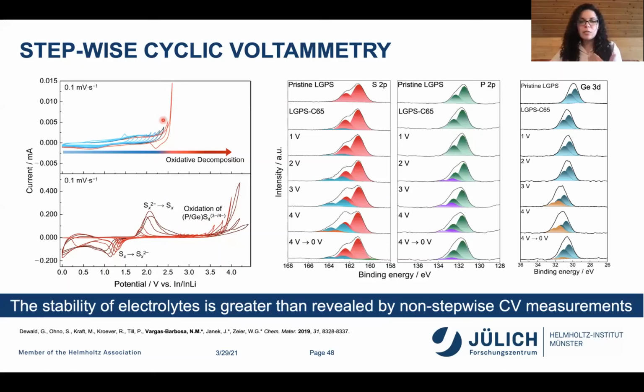But the reality is that it is not the electrolyte itself that is redox active, but the decomposition materials. And this can only be seen when you do it in this stepwise manner, because up until this point, about 2.2 volts, we know that our material is stable. And then suddenly we have redox peaks taking place in the same potential range where our material used to be stable. So that means that our material starts decomposing. It's not super stable, but once it starts decomposing, the redox chemistry that we start observing is actually that of the decomposition materials, and not of the electrolyte itself. So we can simply prevent it.